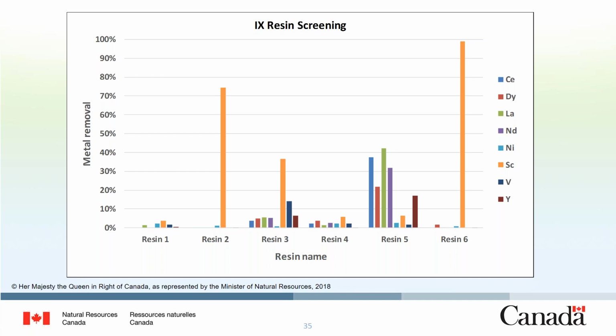This figure shows the percent removal of several elements from the PLS after 24 hours. 2 resins were found to be selective for scandium, while not retaining any of the other metals to a significant degree. In fact, resin 6 removed almost 100% of the scandium while retaining almost none of the other metals in the solution.